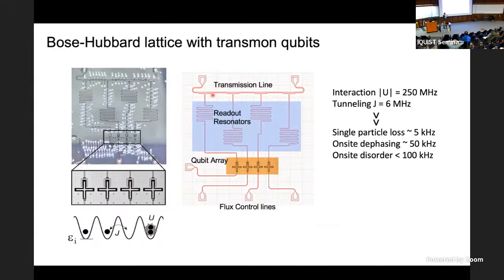Some numbers for this particular device: the on-site interaction, 250 megahertz, is much larger than the nearest neighbor tunneling on purpose. So you are in this very strongly interacting Bose-Hubbard lattice. The single particle loss, which is essentially the lifetime of each of these transmon qubits, is about 30 microseconds, which is about 5 kilohertz. So you can see this starts as a very coherent lattice where a particle can tunnel thousands of times before it's lost. And dephasing and disorder is a little bit worse due to technical noise, but still small compared to both the tunneling and the interaction.